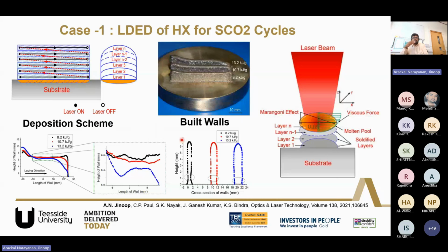So we studied the wall structures in the beginning. We did studies at different parameters, different energy densities, to understand how a stable wall can be generated by using DED technology. The major challenge here is the balance between the Marangoni effect and the viscous forces that act during the process. So we need to find that specific process window, and we tried different trials by varying the delay during the manufacturing.